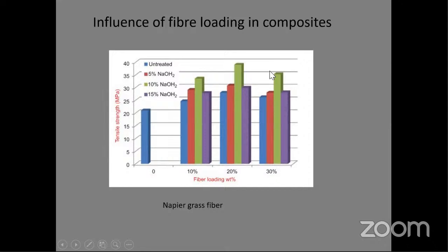This may happen due to agglomerations, and there won't be a proper wetting ability of that particular polymer after it reaches 20%. So more than 20%, the wetting ability of that polymer will be reduced, and the solid content becomes more dry content, and there won't be proper bonding, and still some agglomerations will be formed. Due to that, the strengths will be decreased. So this is what happens when you are going for a higher fiber loading. So some results